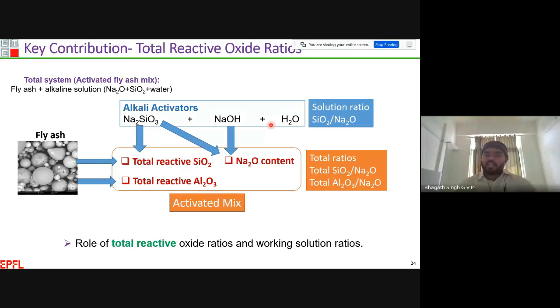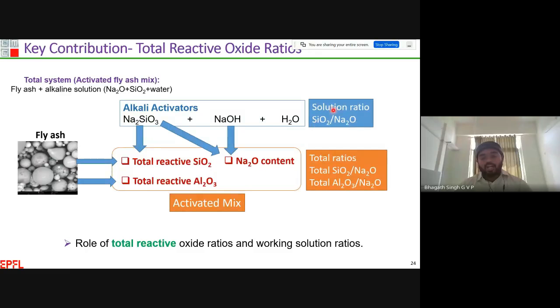Generally, we use sodium silicate and sodium hydroxide as the alkali activators, or some researchers have used potassium silicate or potassium hydroxide as the alkali activators to activate the fly ash. If you use sodium silicate and sodium hydroxide, based upon the sodium oxide as well as silicon dioxide content in the working solution, we call it the solution. And based upon those contents, they have determined the silica to sodium oxide mass ratio in the solution.